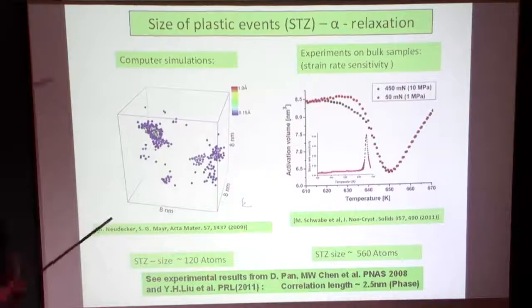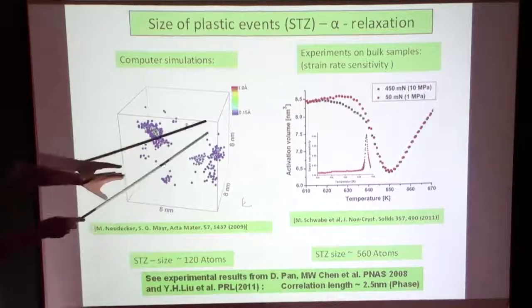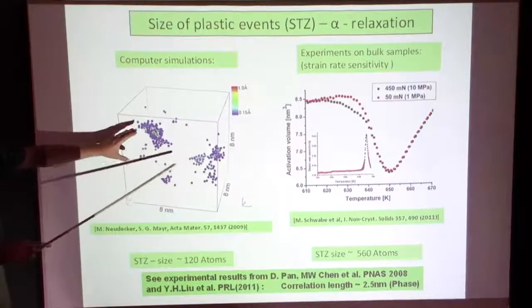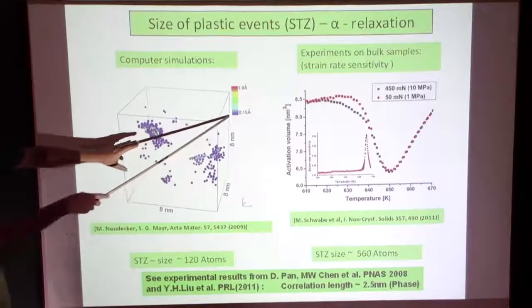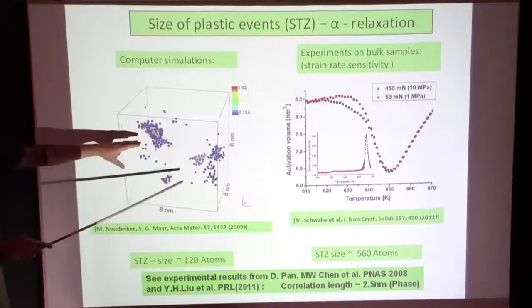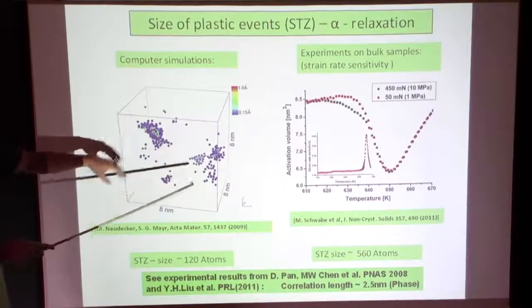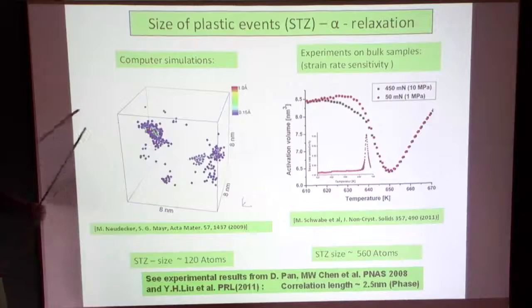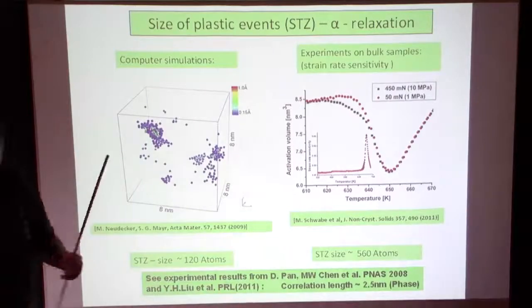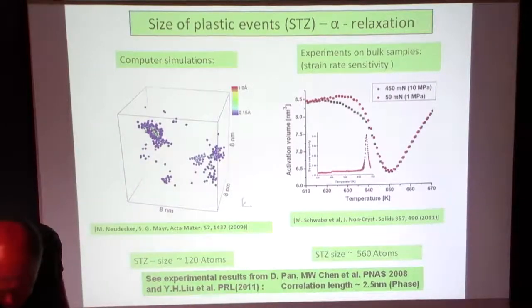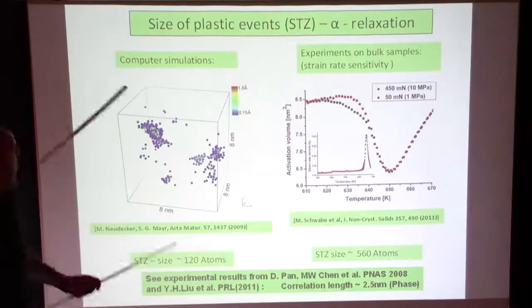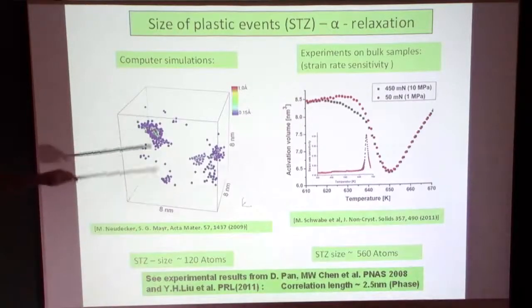For the simulations, are those actual displacements of the particles, or are they inferring something from the inherent structures? They show the displacement of the particles above a certain threshold for a limited temperature, and only those are plotted here. You can look at all, actually. But these are simulations also done with creep? No, this is just simulations without any stress.